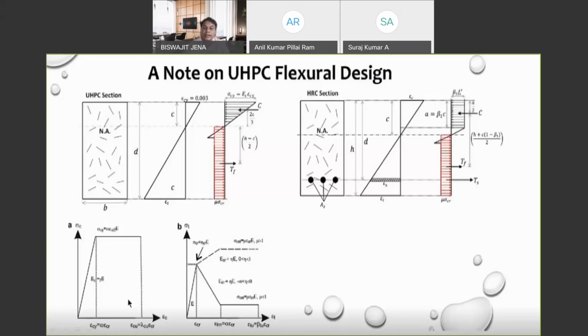The second advantage is what we call a hybrid reinforced section, where you have a reinforced concrete beam with an ultra high performance concrete that has some fibers. So you have a multiple effect. In the area below the neutral axis, you have a tensile contribution of steel, which is the area of steel, plus the tensile contribution of fiber reinforced concrete. You do a constitutive model for compression and tension, and you can see that the constitutive model for compression is a bilinear curve: an elastic increase in compression, and then a plastic region. In tension it is a trilinear curve, where you have an increase in tensile stress, a drop, and then a plastic region in the tensile zone.